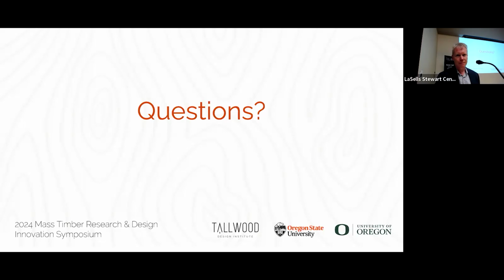Now, the other one is we're looking at the acoustic performance to see if we negate it by doing that. I didn't talk in detail, but we're using one of the specimens for the structural part, and we want to know whether making that connection really breaks down the acoustic performance or increases the coupling, right? If that makes sense, to increase the amount of sound transmission to the concrete. So we have one of the specimens there that will have 4 times the number of fasteners, just to see if they're acting as waveguides to increase the amount of sound transmission through the fasteners, not just the concrete.